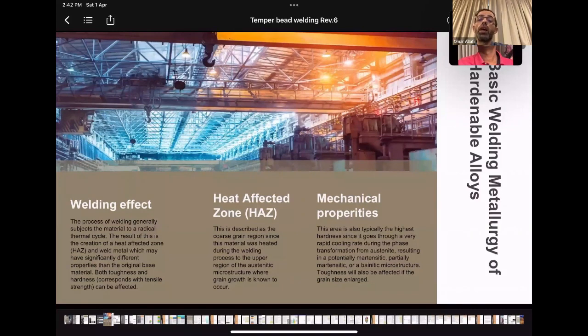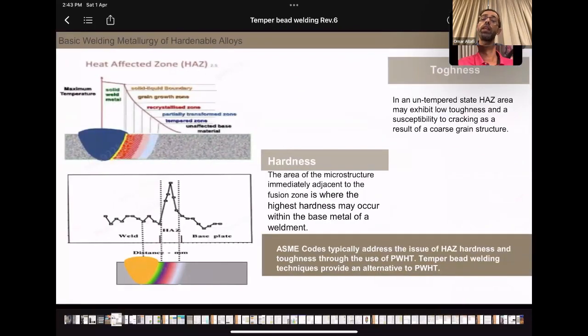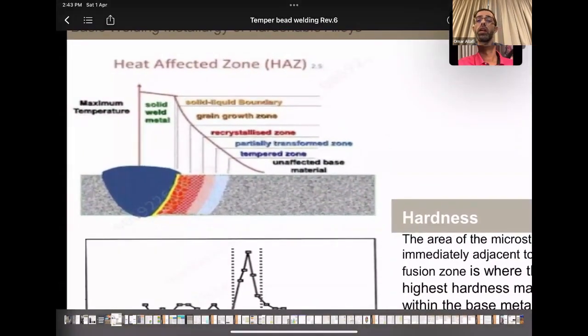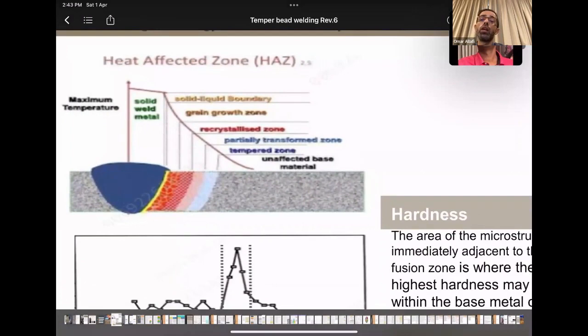This is where the highest hardness can result after welding. And this is where we have a coarsened grain area where toughness might be impacted. It is clear in this graph that the coarsened grain area is adjacent to the fusion line of the weld because of welding.